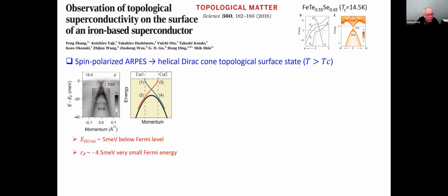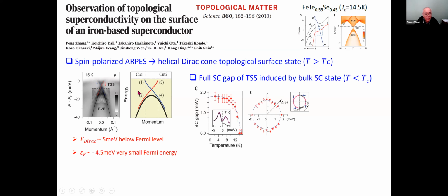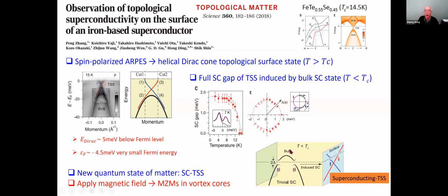Now, everything that they found is actually peculiar of FeTeSe, which played a role in what I'm going to say later. The Dirac cone is about 5 millivolts below the Fermi level. And in fact, the bulk band has a tiny Fermi energy, 4.5 meV of this whole band. Now, if they go below Tc, they found that there is a gap, a superconducting gap developing in the topological surface states. And that's a reason, I think that's evidence that we have for this new quantum state of matter, which is the superconducting topological surface states.